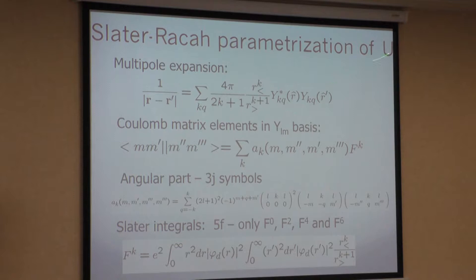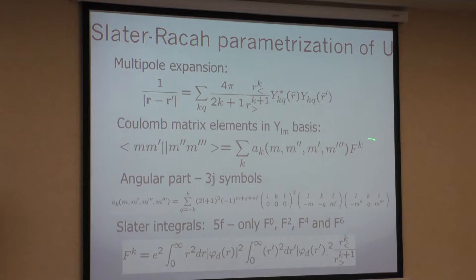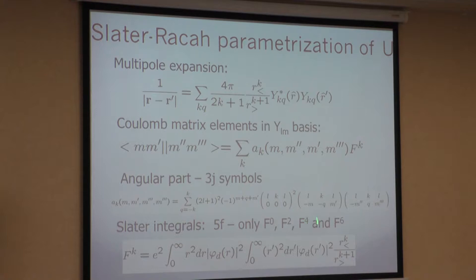From atomic physics you know that the local Coulomb interaction U for an orbital can be expanded in so-called Slater or Racah parameters. You write a spherical expansion for the Coulomb interaction and put it into matrix elements, giving a Coulomb matrix element proportional to the Slater parameter F^k, which is just a radial integral. Some complicated angular parts involve 3j-symbols, but you can tabulate this. You need only three parameters for D states or four parameters for F states — renormalized by screening in solids.